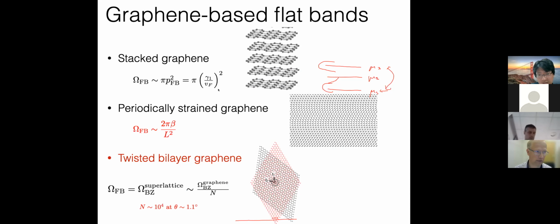So for example, in this case here, the size is determined by the size of the interlayer coupling, gamma 1. Vf is of course just the regular intralayer Fermi velocity. In this case, the idea is that the pseudo vector potential has the form beta over L times cosine of 2 pi x over L, basically. So it's these parameters, the amplitude of the strain modulation and the period of strain modulation, that determine the size of the flat band.